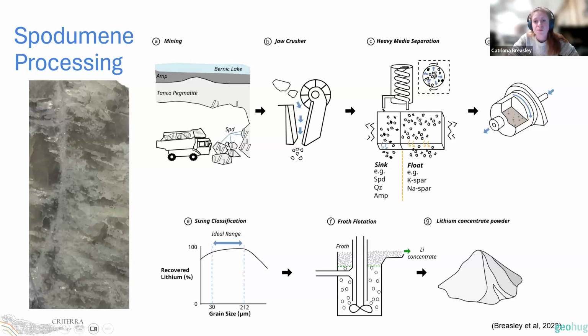This material then goes through the ball mill, where it's ground down to the right size, and then goes through sizing classification. And ideally, we want between about 30 microns and 212 microns. Any smaller than this will produce slimes in the process, and any larger than this, your grains are really going to have a hard time floating to the top during the froth flotation process. So froth flotation then takes place where the lithium binds to the surfactant. It's then brought to the surface and then it's skimmed off, and then you have your wet lithium concentrate, which is then dried.